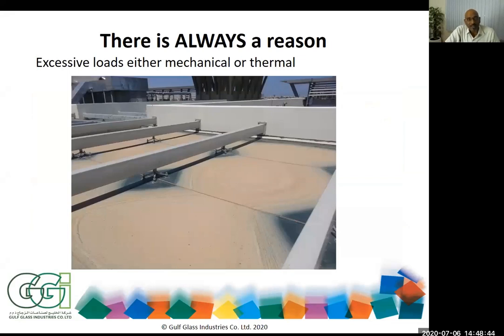There's always a reason, and excessive loads, mechanical or thermal loads. Now, this is not a design on the glass, it's not a printing, but this is how the glass was when we went, because there were glass breakages and they were breaking from the rotules or the spider joints or the whole area. This was a condition with water and continuous load on the glass, with all this dust and sand on the glass. So it was a constant load on the glass. These need to be checked: how close the holes are to the corners, how far they should be, and whether the glass will be able to take the maintenance load and then the service loads.